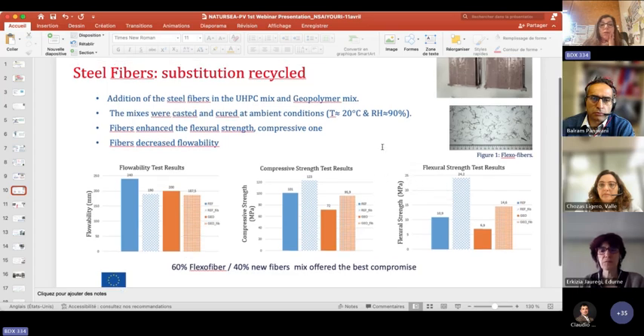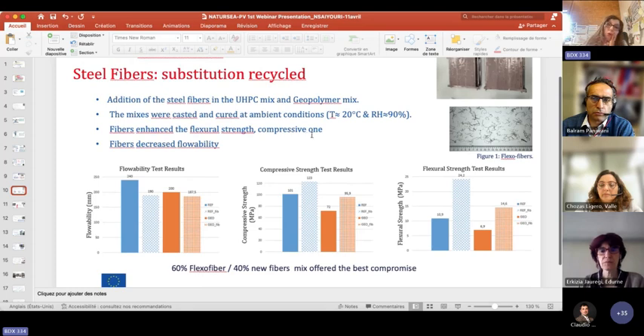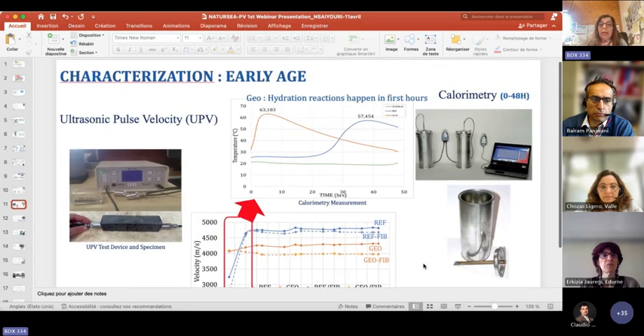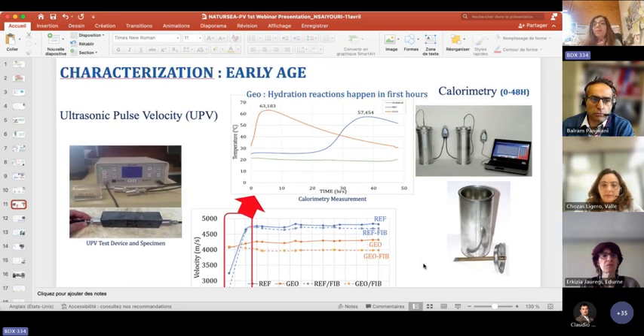So we worked with the new and recycled materials, and we could substitute about 60% flexofiber, which are recycled fibers, and this gives us the best compromise mix with the 60% flexofiber. So we use recycled materials as many as we can. Some characterization of those mixes.